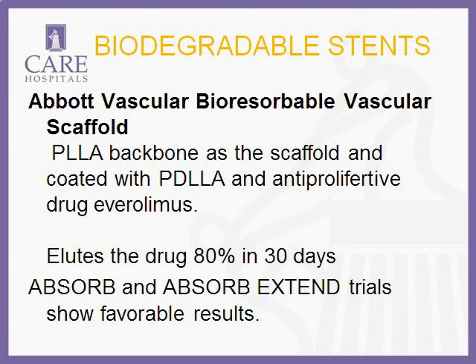Whereas the Abbott Vascular bioresorbable vascular scaffold, they called it a scaffold and not a stent because there is no metal there. PLLA is the backbone of the scaffold and is coated with PDLLA, and it is actually a drug-coated stent with everolimus. We've been part of the trial and seen good results with this. It elutes almost 80% of the drug in 30 days. We've done around, I think, 15 to 20 cases of this and had no bad experiences as such.